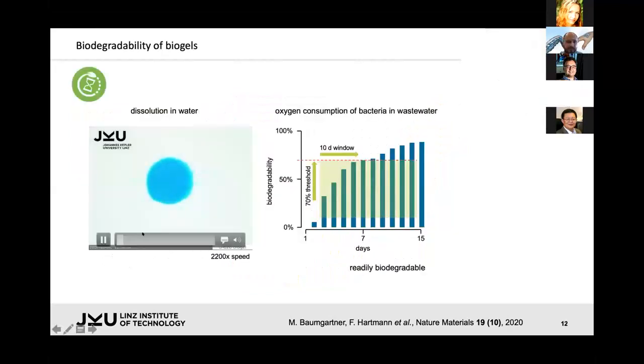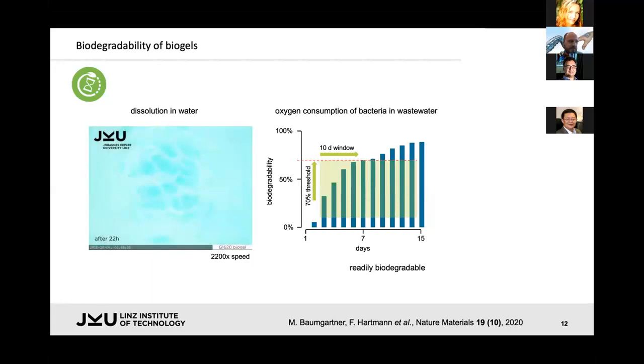We actually tested this biodegradability. On the one hand, as you can see in the sped-up video on the left, this hydrogel still dissolves in water over the course of a day or two. But this doesn't necessarily mean that it's biodegradable, because what you end up with is eventually a soup with polymer chains that are dispersed in water. And if you ingest or inject the material, then these dissolved polymer chains can very easily end up in your kidneys and don't get out of the body.